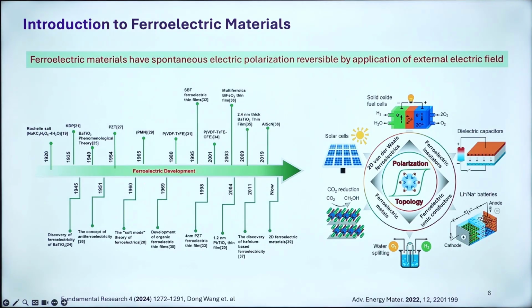Now take scandium nitride, which is a narrow bandgap semiconductor. If you dope aluminum in place of scandium, partly replacing it, they also see interesting ferroelectricity. Bivas Saha from JNCASR is actively working on the experimental part of this aluminum scandium nitride. Scandium nitride is a simple rock salt type structure, and if you dope aluminum on scandium, it shows interesting ferroelectric properties. Now they try to see this kind of behavior in several compounds, and the applications include solar cells, fuel cells, dielectric capacitors, solid state batteries, water splitting and so on.